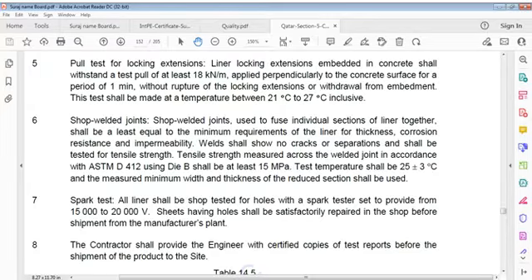Shop-welded joints I was talking of. So sharp welded joints used to fuse individual sections of liner together shall be at least equal to minimum requirements of liner for thickness, corrosion resistance and impermeability. Weld shall show no cracks or separations. Shall be tested for tensile strength. Tensile strength measured across welded joints in accordance with ASTM D412 using die B shall be at least 15 MPa. Test temperature shall be 25 plus minus 3 degrees Celsius.